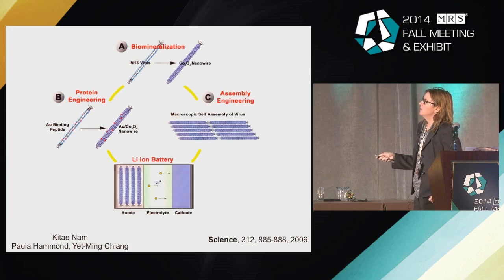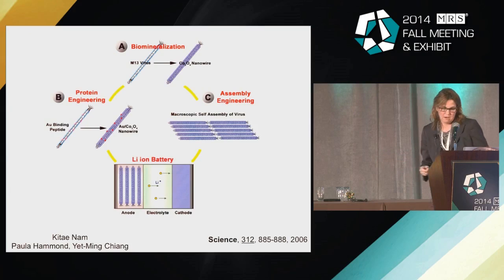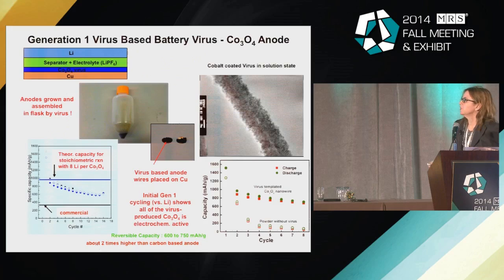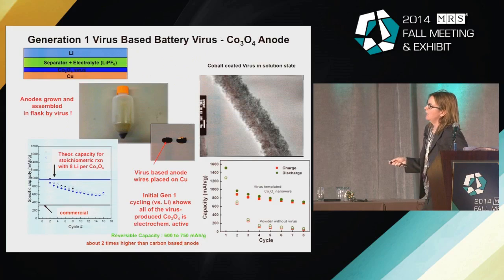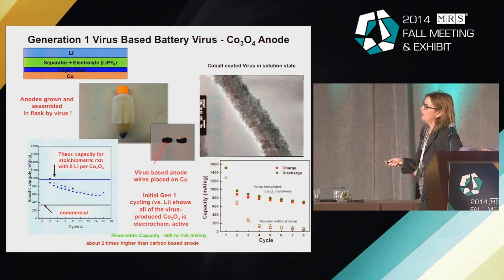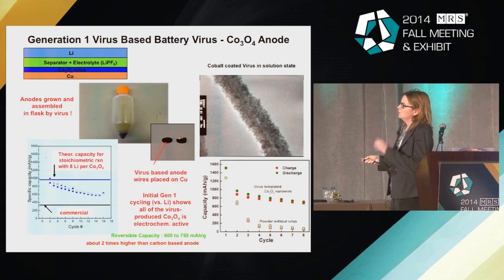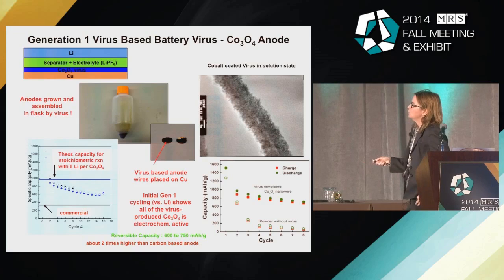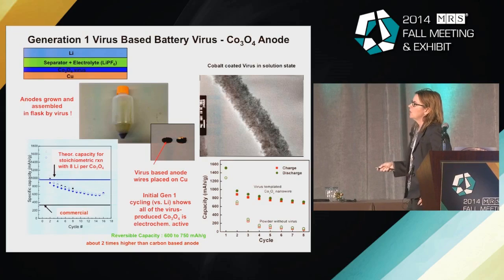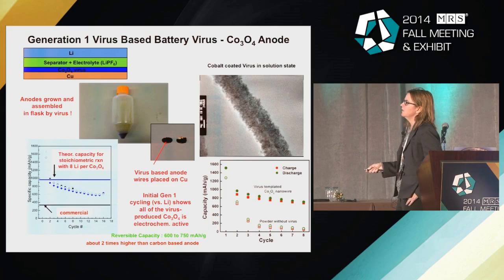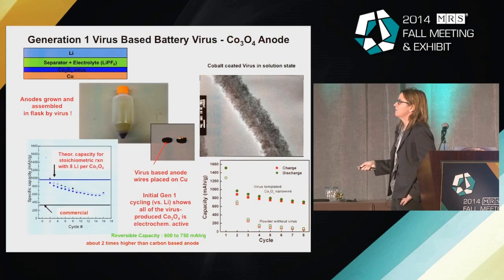Then we use the power of biology to self-assemble these materials and make it into a functional battery. Basically, you make it just at the bench where you have your virus sequence. You give it a cobalt source, and you're able to nucleate these cobalt oxide nanoparticles, and then we can test it as a battery electrode. So this is specific capacity versus cycle. This is commercially available. This is theoretical capacity, and this is what our first virus battery looked like.